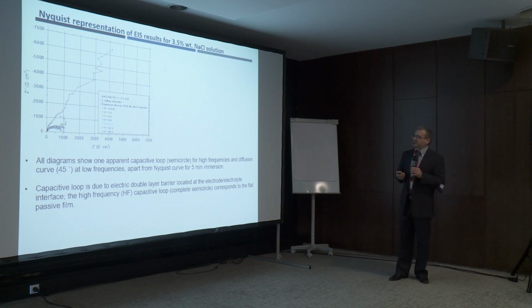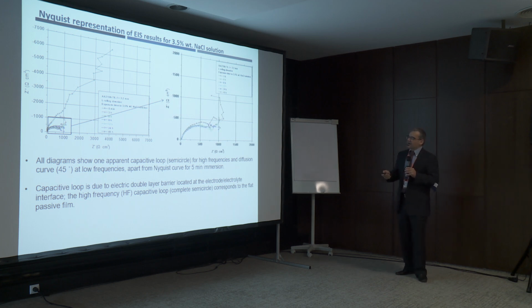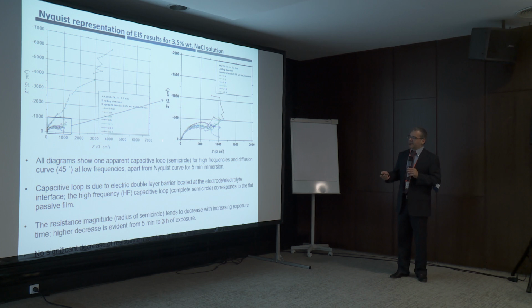What do we need this Nyquist plot for? As you can see, all these are capacitive loops, and we have an identification that something happens. For example, yes, we have a corrosion mechanism ongoing. The first one is that the protective layer, the passive layer, breaks, and then we have a degradation of the material itself. So it's actually more or less a measure to qualify the ongoing corrosion.